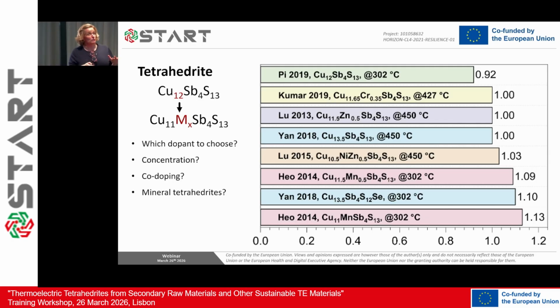So first of all, which dopant should we choose? What's the concentration? Should we co-dope? We found out that it's a very good solution to co-dope, especially because this is what happens in mineral tetrahedrites. Then, of course, we are mixing synthetic and mineral, and we need to come up in the end with compositions which are optimized or as close to optimal as possible. But it was very confusing.